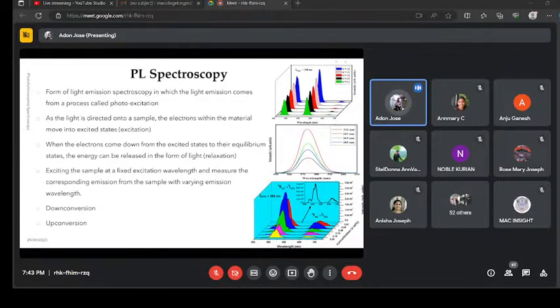This type of luminescence is commonly called down conversion. Whereas an interesting area of photoluminescence research is up conversion techniques. There are certain materials which usually show this up conversion phenomenon. That means we provide a lesser energy light falling on a particular material, and we can observe greater energy than the excitation energy that we have provided. In the last figure, the excitation wavelength provided is around 980 nanometers, and the spectrum is recorded in the range of 500 to 700 nanometers, with the intense emission peaking at around 575 nanometers.